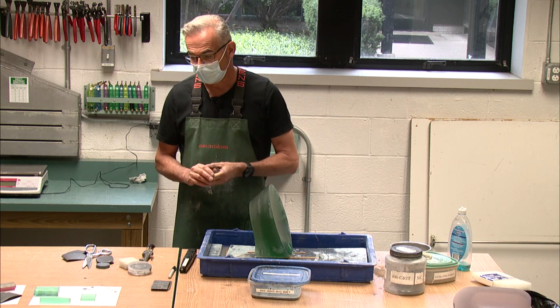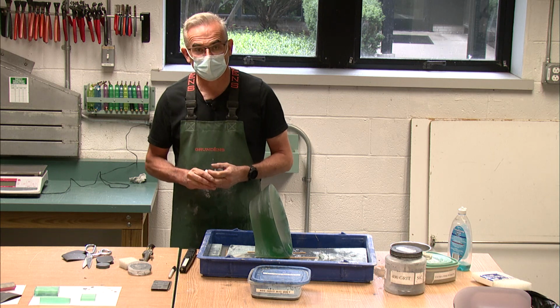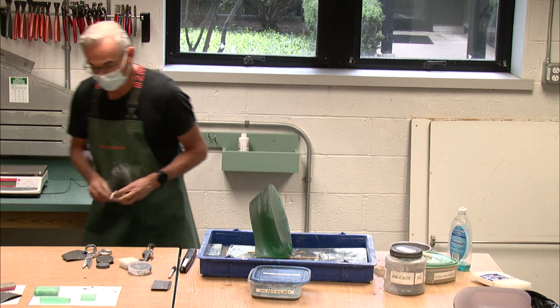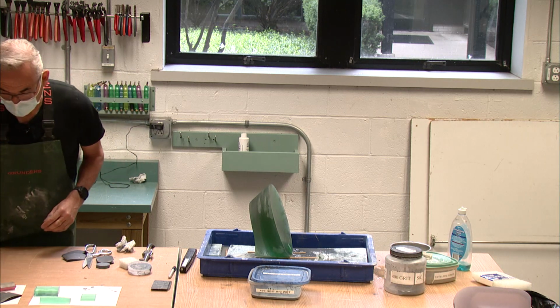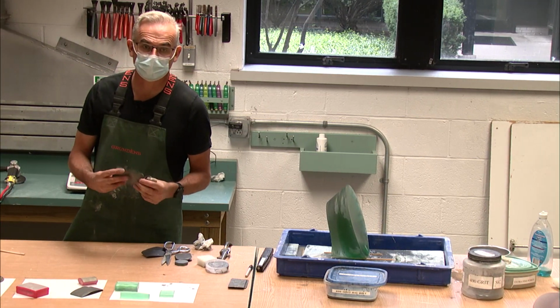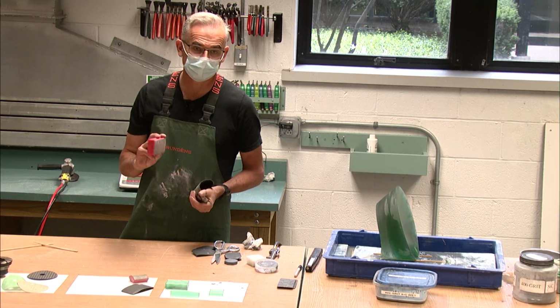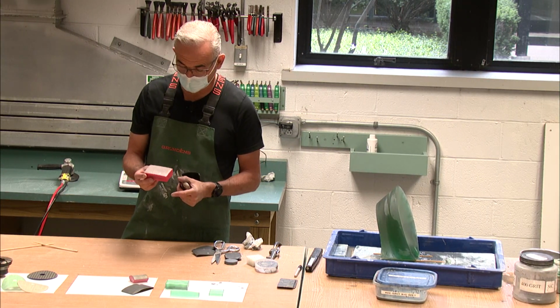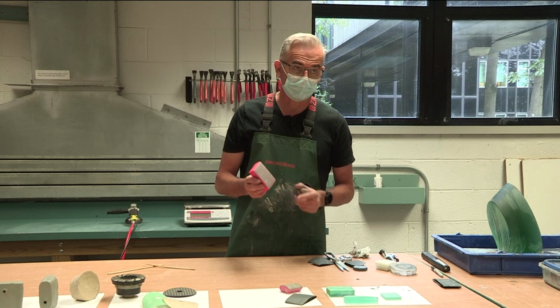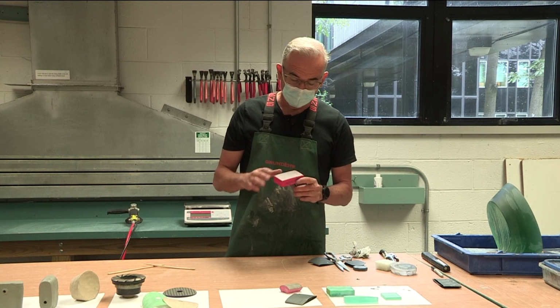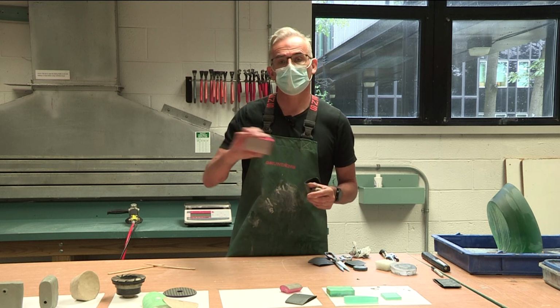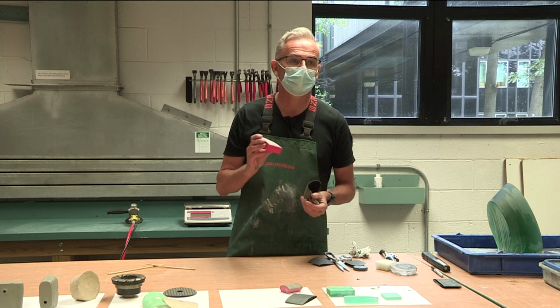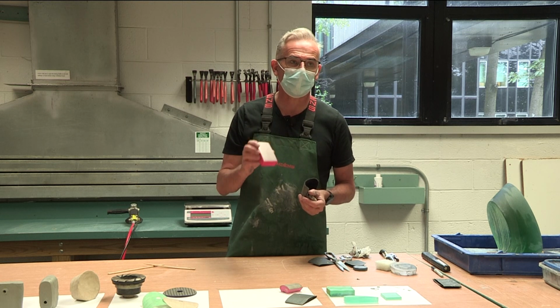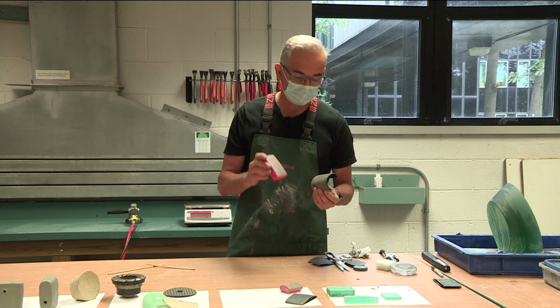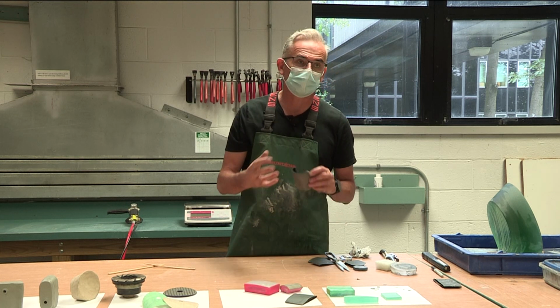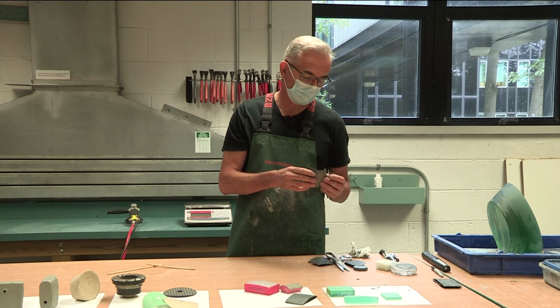And I've used, as I say, a lot of different tools over the years. If we just step back here, here are some. This is like your standard diamond pad that again you'd buy from a stone supplier or an art glass supplier, and that's got a little diamond impregnated sheet on it, and it's flexible and you can buff it around a lot of different surfaces. But that'll give you quite a scratched surface. It's pretty good at evening things out, but it will give you a scratched surface. So I always finish that with the grits.